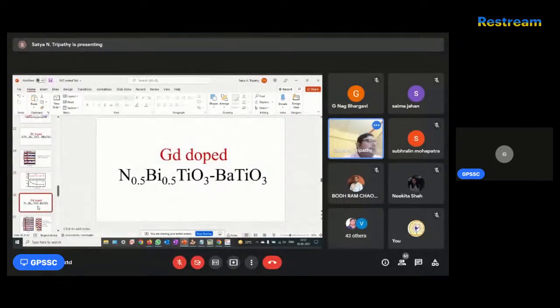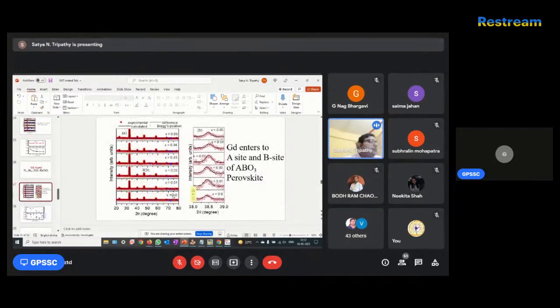Next is another sample, the gadolinium NBT system. Here gadolinium can go to the sodium, bismuth, or barium site. Here one peculiar feature we observe is very important: amphoteric behavior. Gadolinium may go to the titanium site. Okay. So what we observed, we fitted the data with the A site also, the B site also. I am presenting the data of the fitting for the B site as well as the A site. The best fit we observed for the B site. This is the data and these are the fittings. Okay. Superstructure reflections are available at 39 degrees. Here we conclude that gadolinium is actually going to the A site as well as the B site.